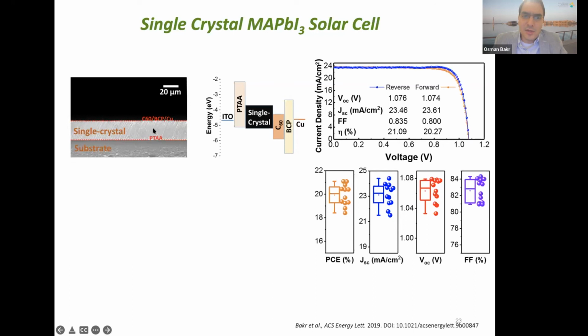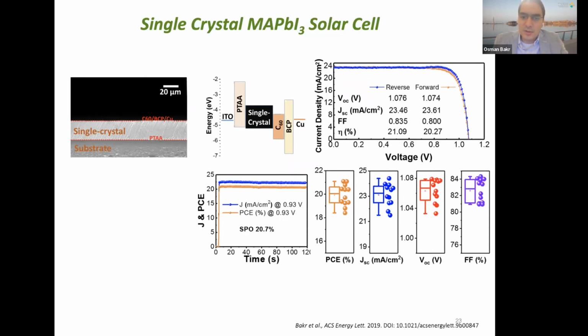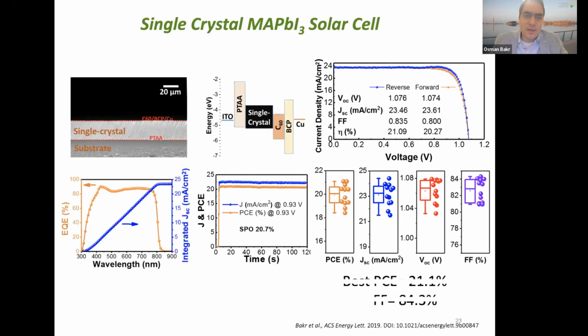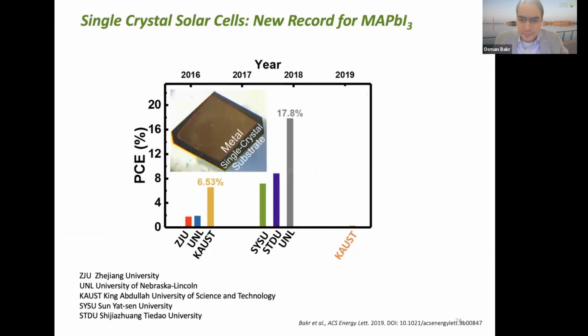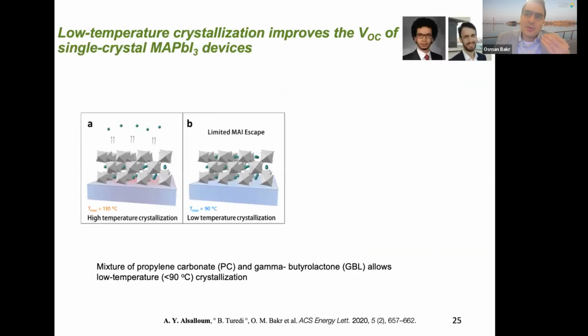Normally a thin film solar cell would be a few hundred nanometers. This single crystal solar cell is about 20 microns thick. And yet, despite this, the efficiency was really high. We had 21% efficiency even for our first generation of devices. So this was a big jump in efficiency of single crystal devices. We started looking at how to improve this further.